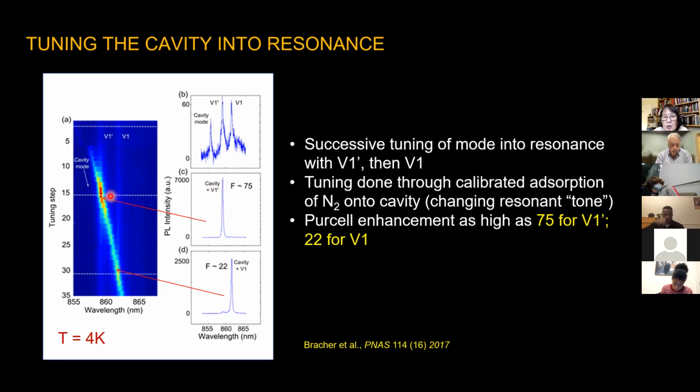What we do to tune is we actually change the resonance state of the cavity by actually absorbing gas. So we tune it just as you have a wind instrument and you can tune that wind instrument by the thickness of the wood or changing the geometry. That's what we're doing. We're changing the geometry reversibly. And so it can be seen, with each tuning step, the resonant wavelength.